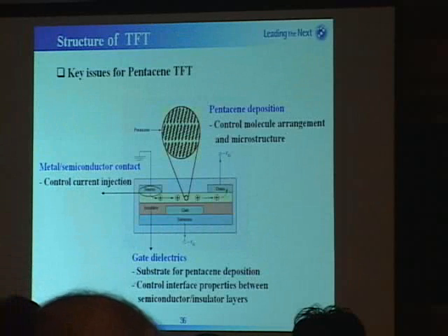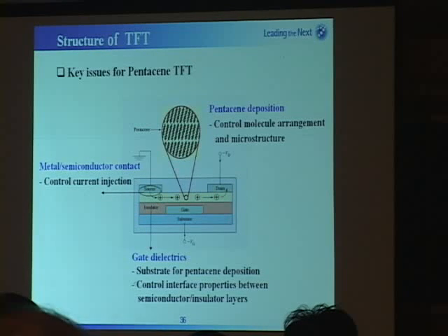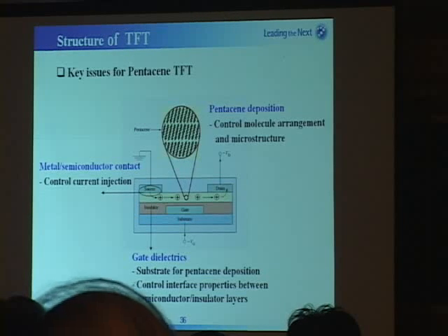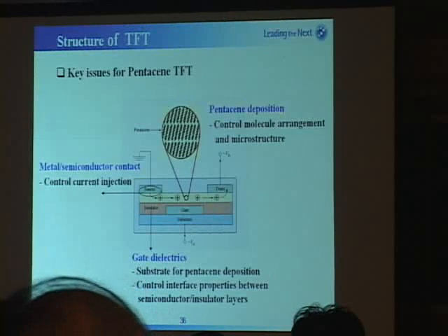This is the structure of TFTs. Source, drain, gate, and on the gate insulator and semiconductor layers are formed. There are three key issues for pentacene TFTs. Pentacene deposition, controlling molecular arrangement and microcrystal structures, is important.